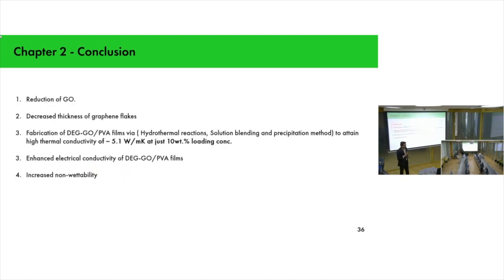So the conclusion of the second chapter: reduction of graphene decreased the thickness of graphene flakes, very high thermal conductivity was achieved at a lower weight percentage, and non-wettability increased.